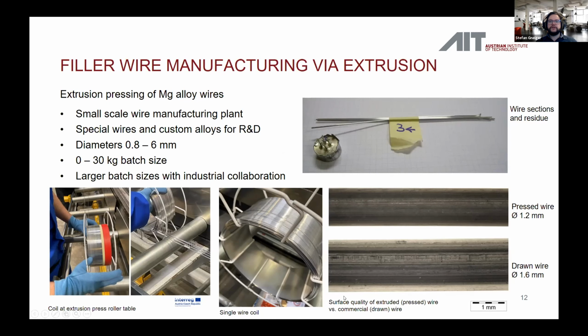And on this picture, you can see the surface quality of extruded wire. Here the extruded wire with a diameter of 1.2 millimeters. And here you can see a commercial drawn wire with a diameter of 1.6 millimeters. So the surface quality is comparable in both cases.